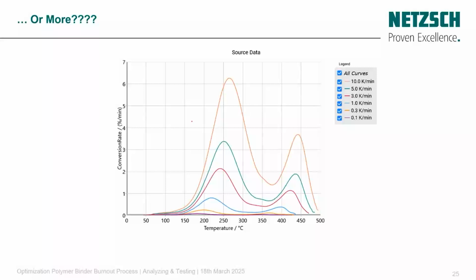So in this case, we use the conversion rate, and clearly here you can see that we have 2 peaks, which confirms for us the result that we have only 2 steps. Also, we can use the DTG, the derivative thermogravimetric analysis, which represents the rate of weight change with time, which can also give us an idea how many reaction steps we can apply.